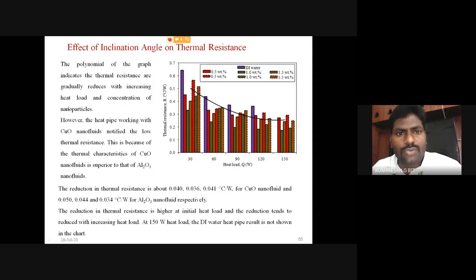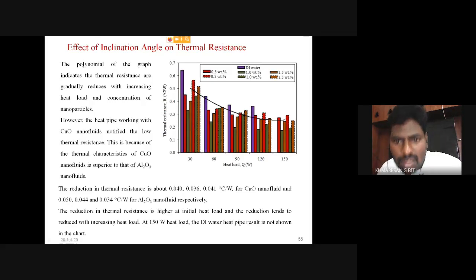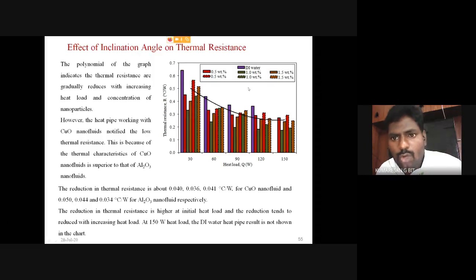Then the effect of inclination angle on thermal resistance. This graph shows that by increasing the inclination angle and by increasing the heat input, the thermal resistance gradually reduces irrespective of the nanofluids we are using.